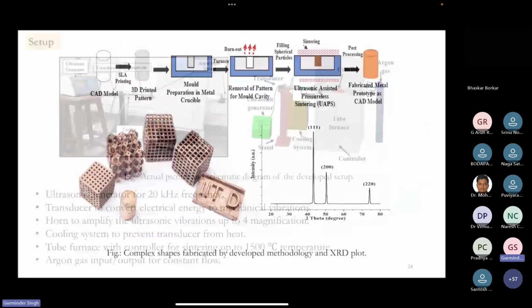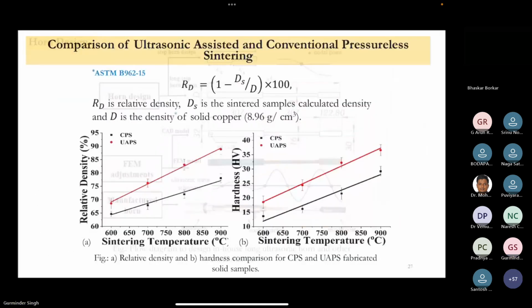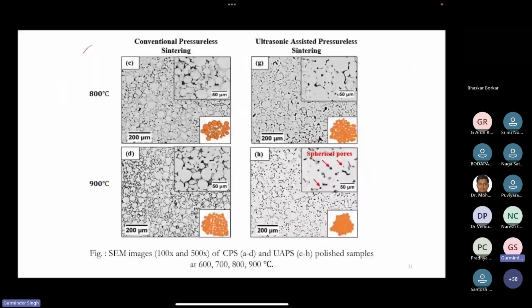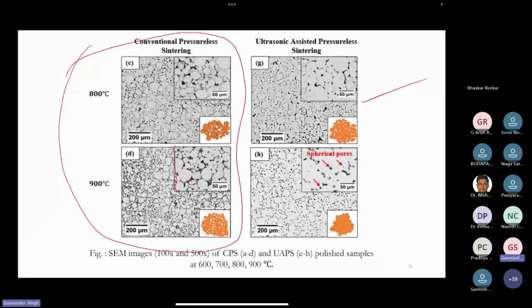Let me first show you some results on why we need vibration. On the left hand side SEM, you can see this is without any use of vibration, and the right side is with vibration. When using spherical particles, there are a lot of voids between them. But with ultrasonic pressureless sintering, you can easily get spherical pores at around 900 degrees Celsius, and it is done in 15 minutes. To achieve this at 900 degrees Celsius with conventional sintering, you have to do it for 3 to 4 hours.